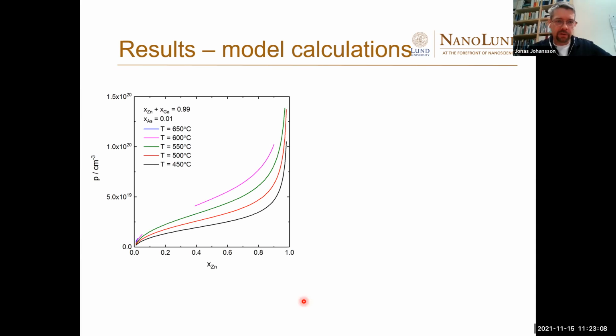Here is for self-catalyzed growth. So zinc plus gallium is 99%, and arsenic is 1% for increasing temperatures. So you see that for low temperatures, we can cover the entire range, but here at 600 degrees, there is a range here where we don't have any doping, and here where we don't have any doping. And the reason is that we cannot grow there.